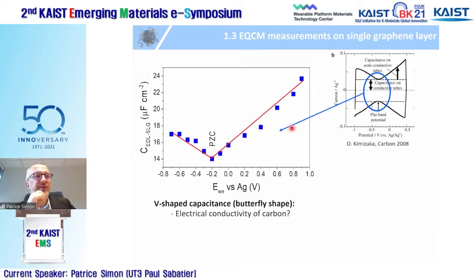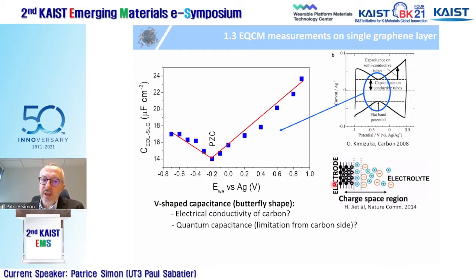Several explanations were proposed in the literature to explain this shape. The first one is a change of electrical conductivity of the carbon. So here the minimum corresponds to the minimum conductivity of the single layer graphene. The second one was proposed with the influence of a quantum capacitance. Basically, you have a small charge carrier density in a single layer graphene. And then this minimum corresponds to the limitation from the charge carrier density side of the SLG. So these two hypotheses deal with limitation from the carbon side.